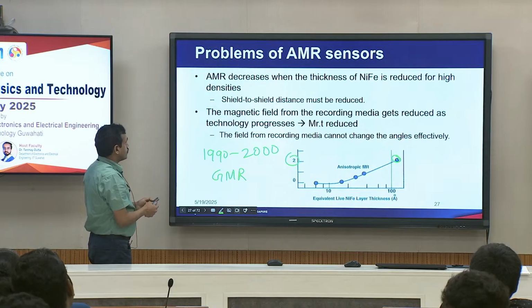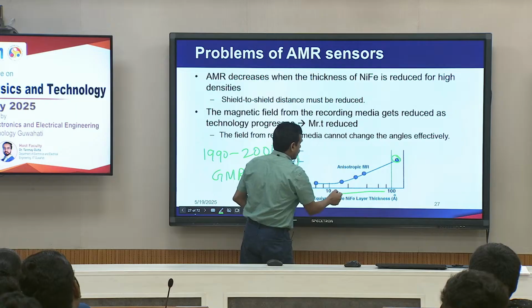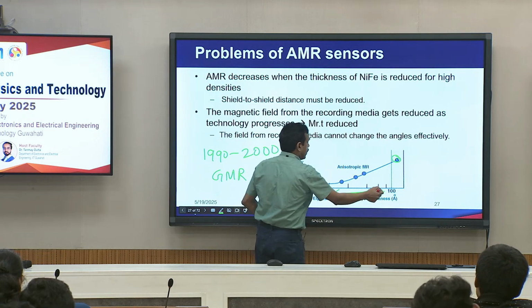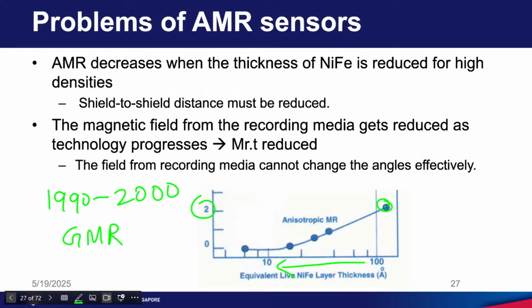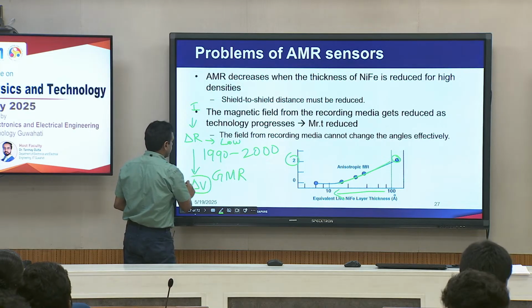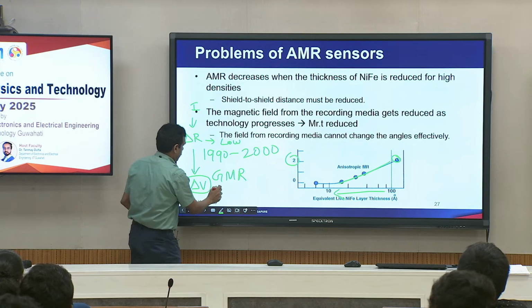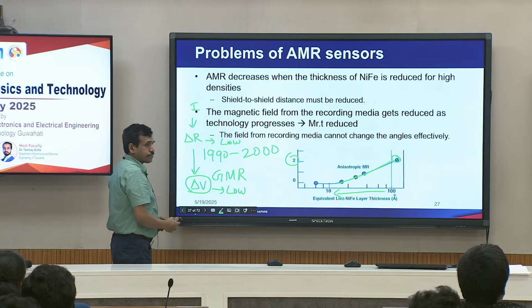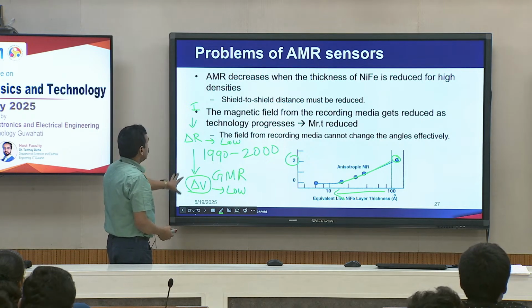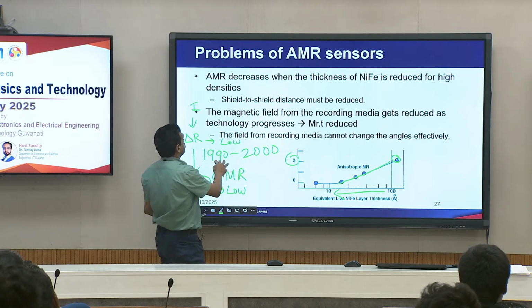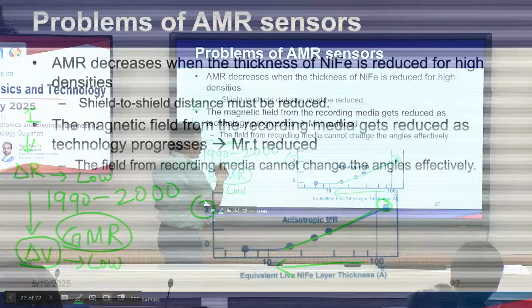When the AMR element thickness is reduced, you can see that when you go from 100 angstrom to 10 angstrom, or 10 nanometer to 1 nanometer, the magnetoresistance is also decreasing, which is not good, because your delta R is small. When the delta R is low, let us say you send some current through the sensor to sense, the voltage change you see will also be low, delta V will be low. Because of this reason, people moved away from the AMR technology to GMR technology, giant magnetoresistance technology.